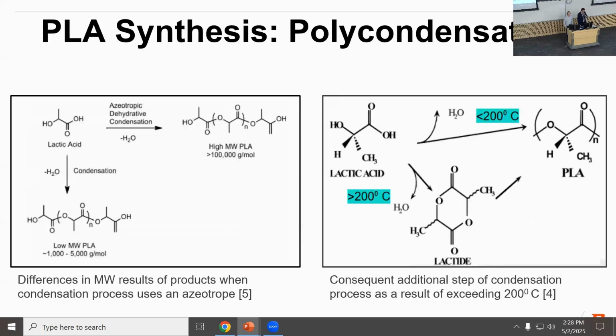So in the image you see on the left, this shows you the two different products you could get, whether or not you use an azeotrope. If you don't use one, less water is removed and you get a consequently lower molecular weight PLA. It's not as strong, it's not as ideal. If you add an azeotrope, you lower the boiling point of the solution in general, get rid of more water, and you're left with higher molecular weight PLA, which is what you'll typically want.